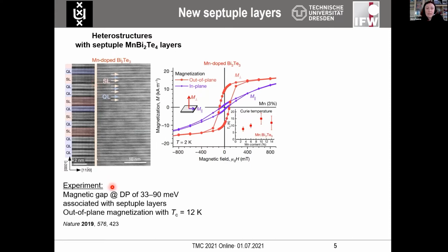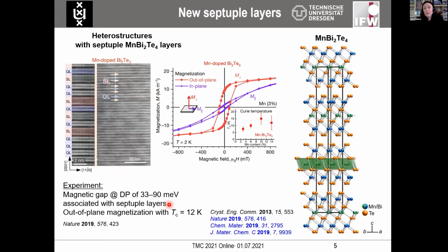Even more interestingly, these heterostructures of quintuple and septuple layers also showed quite larger magnetic gaps than was anticipated by theory for a manganese doped, extrinsically doped bismuth telluride. Further on, people started approaching the septuple layers from a different side.